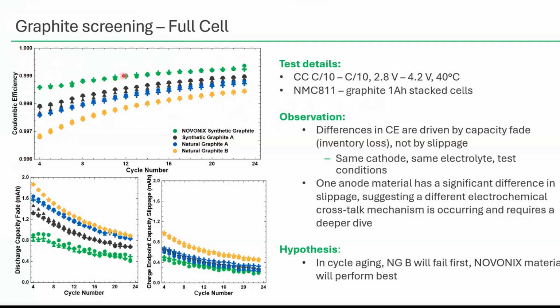All of this might just be within the noise of the other data sets. We see these really consistent differences in coulombic efficiencies, cell to cell. And when we break this out into the fade and the slippage term, like I said, we see almost a flip of what we saw in the cathode, where in cathode we were driving these differences with charge endpoint capacity slippage, and we saw basically the same capacity fade rates.